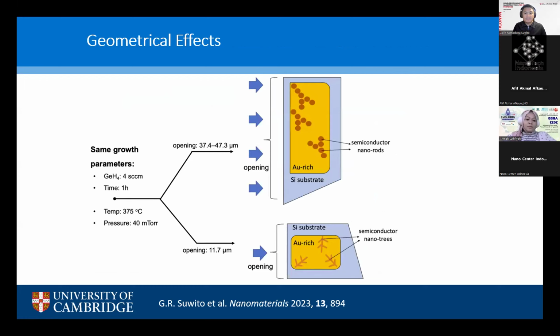Okay, so our investigation so far suggests that different openings, larger and smaller, give us different nanostructures, and this relates to how much germanium precursor gas cracks on the gold catalyst. If you have larger germanium doses, you would have more globular eutectic, and if you have less germanium, you will have more dendritic. And if you're from a metallurgy background, you would understand this as the common lamella and rod features in metallic eutectics.